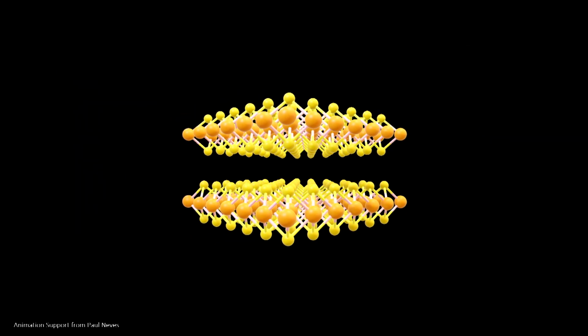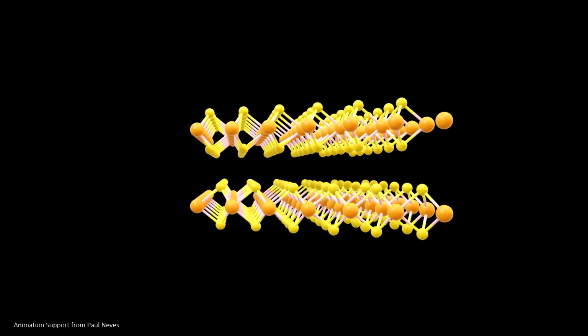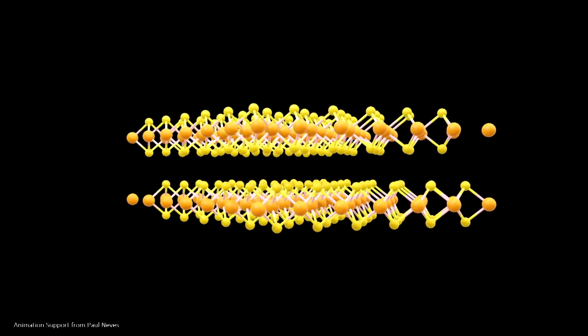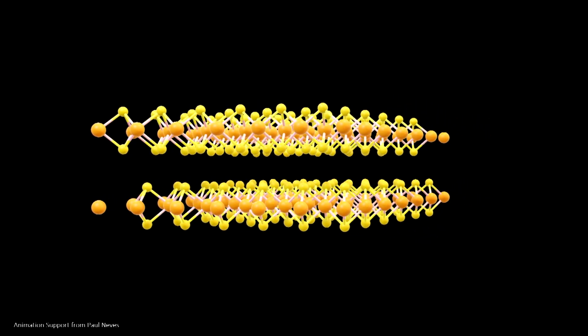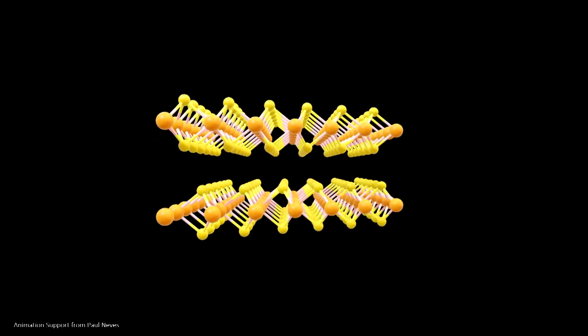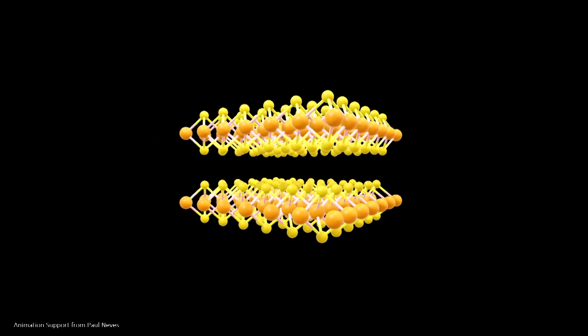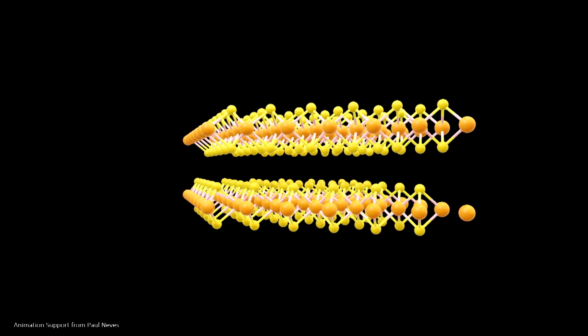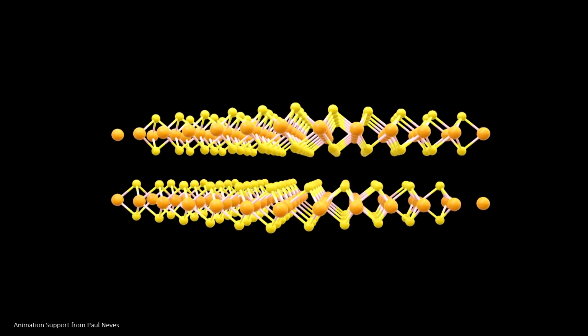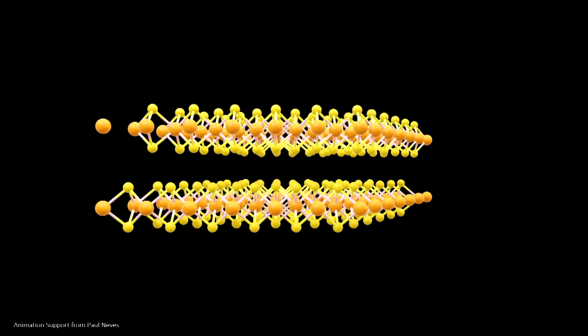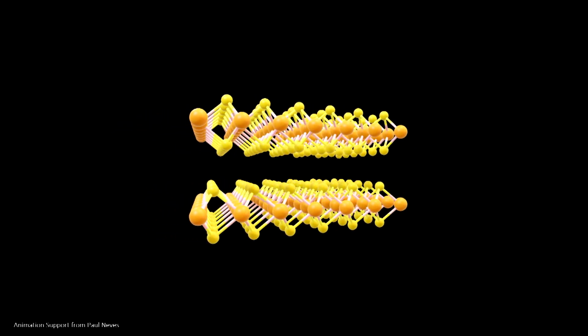So here's one of those transition metal dichalcogenides. This is niobium disulfide. These niobium orange atoms are in the center in this corrugated lattice of sulfur atoms. These are superconducting layers where the electrons spend most of their time, but electrons sometimes hop across this so-called van der Waals gap, which separates the superconducting layers. That kind of thwarts the two-dimensionality of these materials.